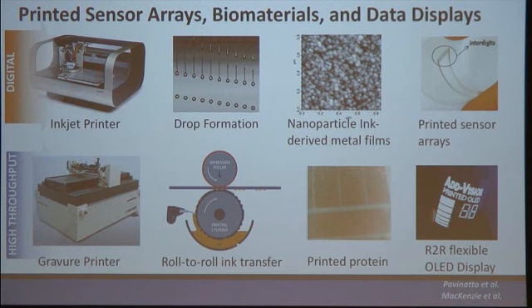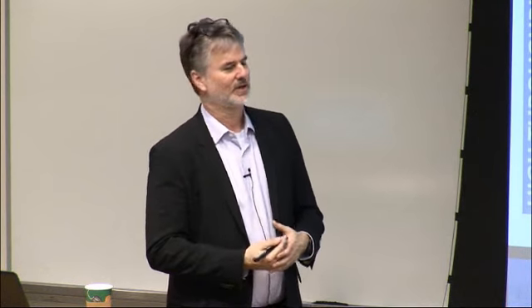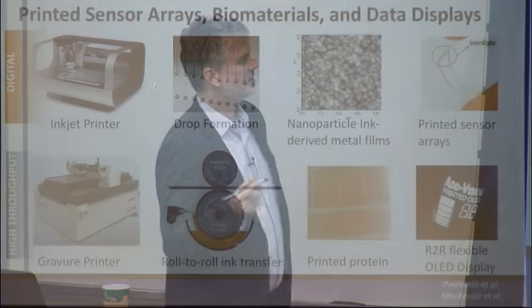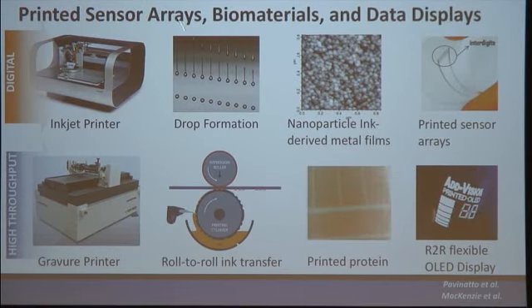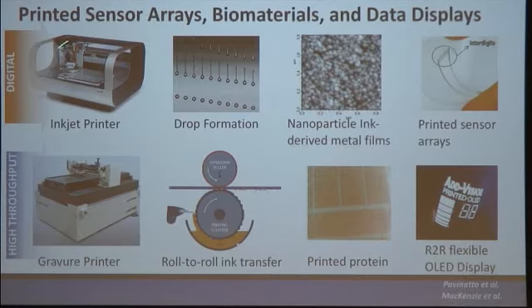Graphic arts resolution, you're talking about 50 micron, 100 micron features at the smallest, and typically bigger. You don't want to make anything smaller than what you can see. It's graphic arts after all. In electronics, we want to push into low micron or even submicron scale imaging. So these are much higher spec. Instead of a $99 printer, this is a $25,000 printer. But still, functionally, you feed in image control data, and you can raster and drop on demand digitally print an image.